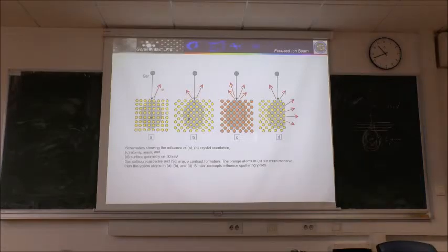Here are some examples of what else influences the intensity of the signal. The influence of the crystal orientation is very important. Here is the so-called channeling effect. What does it mean? If you have the orientation where the gallium is coming from up to down, and you have some kind of channels here, this gallium can penetrate quite deeply inside the material.